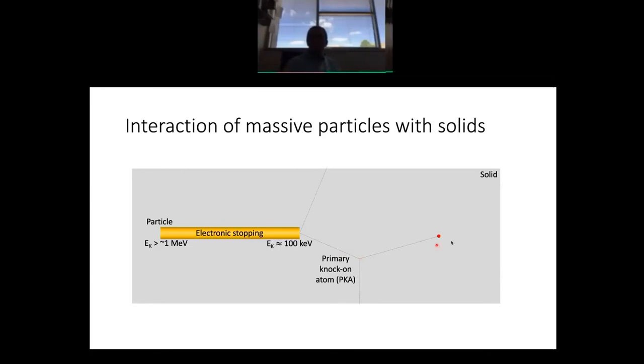Okay? Eventually, when the energy of one of these knock-on atoms gets low enough, its mean free path becomes so small that it basically dissipates all of its energy in a very, very short distance, and you get what's known as a thermal spike. Thermal spike is basically just a region of space that momentarily heats up to very, very high temperatures, on the order of multiple thousands of degrees, maybe up to 10,000 degrees, depending on the material and the energy of the particle. But it's very brief, heats up, cools down very quickly, and that thermal spike is actually what generates defects, right? That thermal spike is the thing that generates most of the damage caused by radiation in a solid.